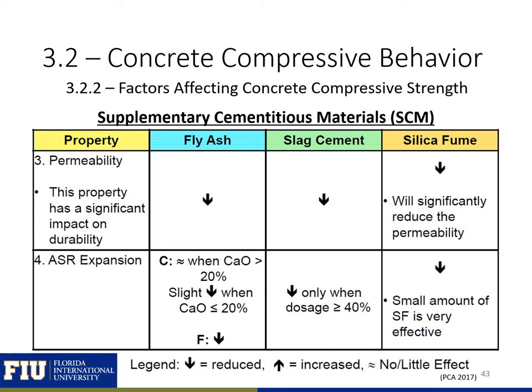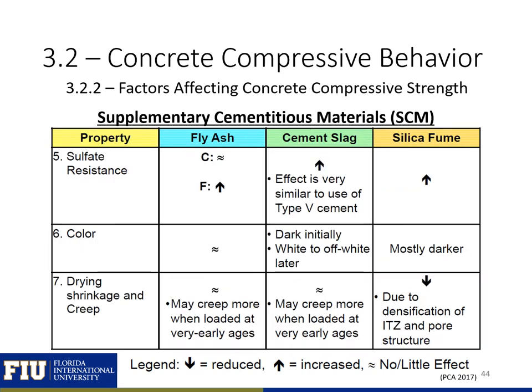Class F fly ash, slag cement in large dosages, and silica fume can also be used to prevent alkali silica reaction, or ASR expansion, which can occur otherwise when reactive aggregates are used. Class F fly ash, slag cement, and silica fume can all also be used to improve the resistance of the concrete to external and internal sulfate attack. Again, SCMs are primarily used to improve the durability of concrete.